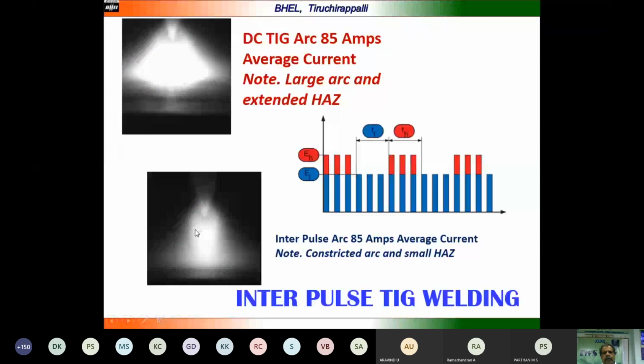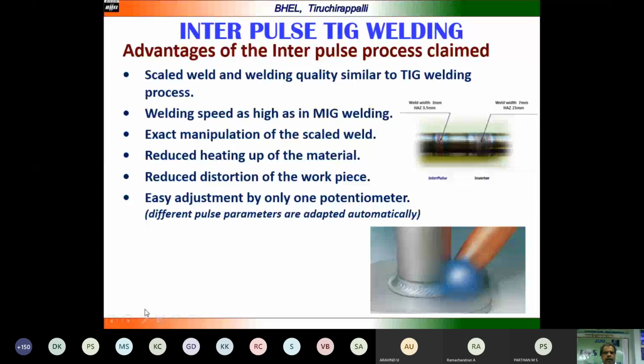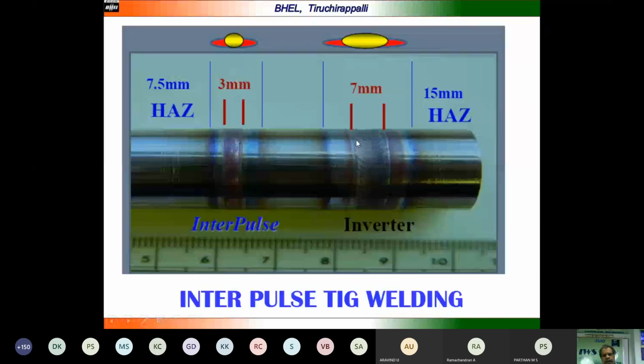It gives scaled weld and welding quality similar to the TIG welding process. Welding speed is as high as in MIG welding. Exact manipulation of the scaled weld can be done. Reduced heat input to the material. Distortion of the workpiece can be reduced. Easily adjustable, and it is having very good quality actually. And you can see the bead width of the interpulse weld and the conventional TIG welding: 7 mm, it is 3 mm here. The heat affected zone is 15 mm here, 7.5 here. These are the advantages of interpulse welding, where you can weld very small thickness titanium and other alloys very easily.